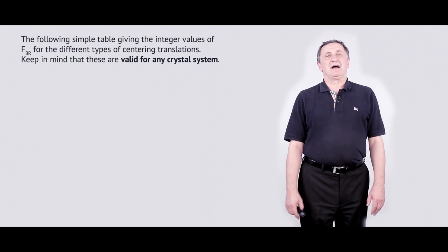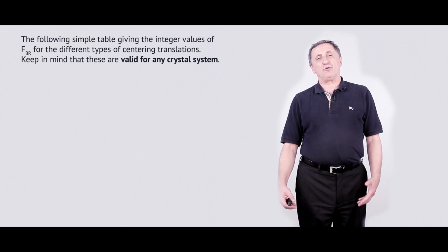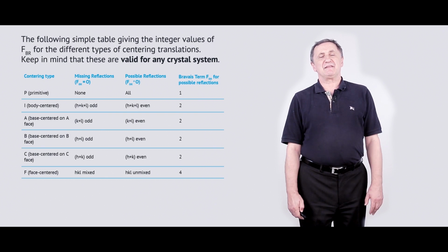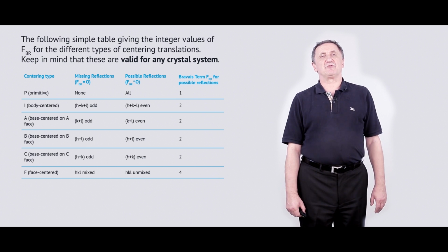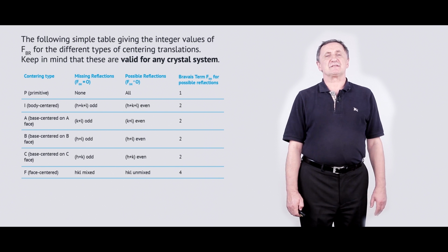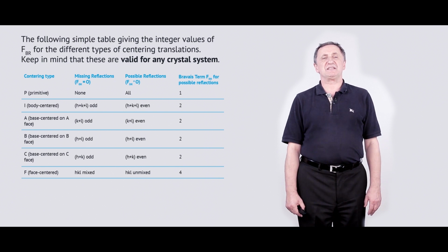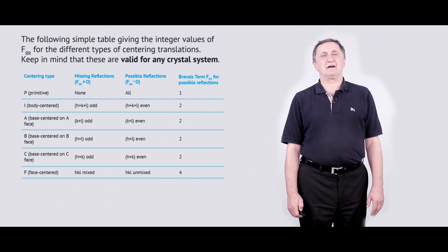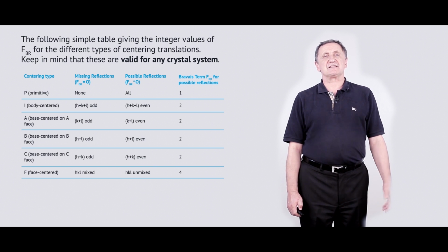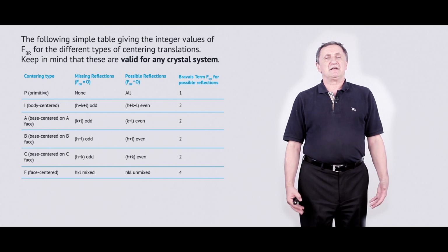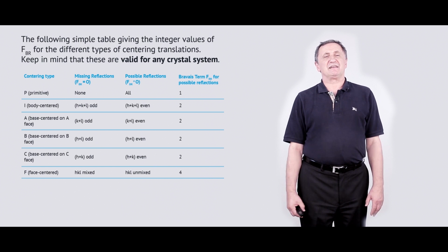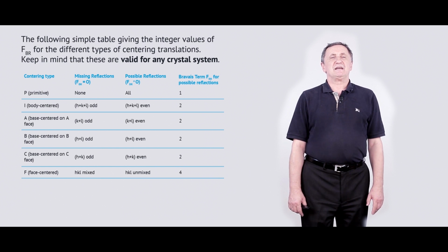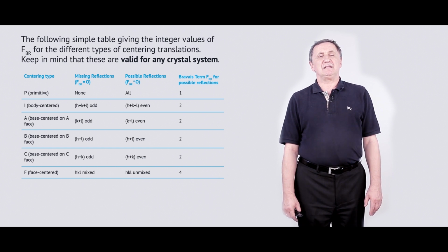Of course, that again can be made manually or with the help of the software, and then you make a conclusion about the crystal structure of your material. Same approach you can use for the tetragonal pattern, slightly more sophisticated, of course, relations between d-spacing and parameter of the tetragonal in this crystal structure. Same for orthorhombic, so every time, same approach, and this allows you to define the phase composition of your material. One exemption, a very important one, is again coming back to indexing.